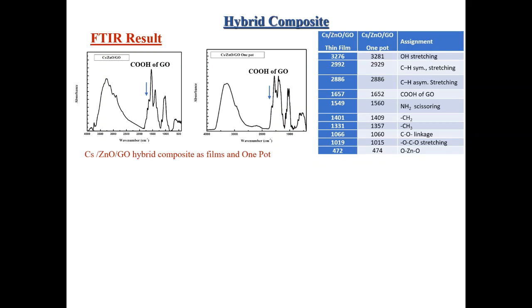There is a shift in the NH2 group to higher wave number, 1549 and 1560 cm-1. These shifts reflected the interaction between chitosan and zinc oxide through NH2. Then a relative shift to higher wave number for the zinc oxide band around 472 and 474 cm-1, which is attributed to the carboxylic functional groups formed by the interaction of zinc, oxygen and carbon.